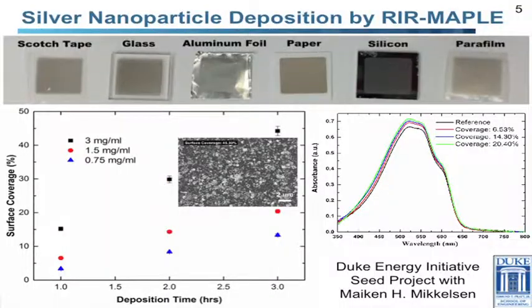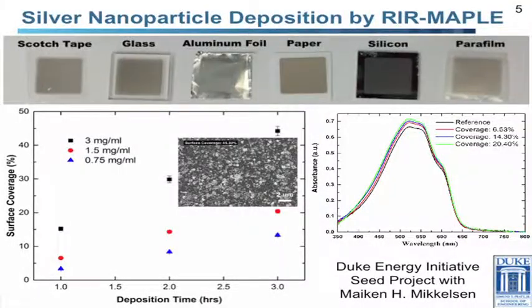And then we also showed that we have very regular control over the surface coverage of these nanoparticles. So controlling the concentration of our target or controlling the deposition time, we get very regular behavior in terms of how these nanoparticles cover the surface. And then finally, we can demonstrate that for these different coverages, we get enhanced absorption in a polymer film. And that's based on this idea of plasmonics, or the special interaction between a metal and a dielectric layer, in this case, the polymer. So controlling the coverage controls this enhanced absorption, and we think that will help with the tandem structures. Thank you.